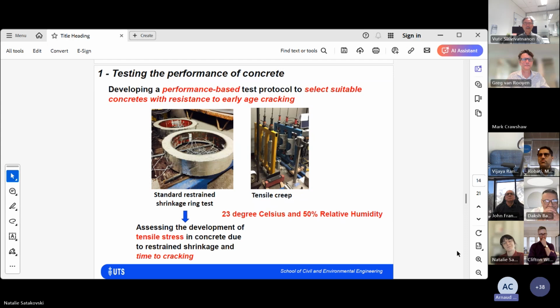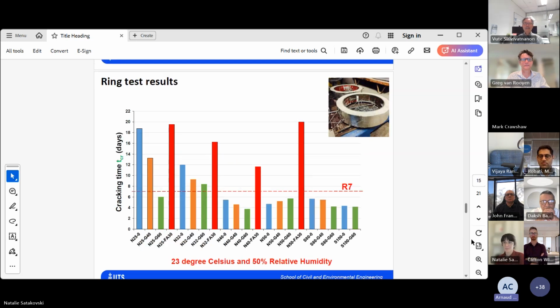That test is really about testing the performance of concrete, specifically targeting early age cracking, just like we do with other durability tests. What we try to look at is how long it takes for the concrete ring to crack in standard conditions, 23 degrees and 50% humidity. And next slide, please.